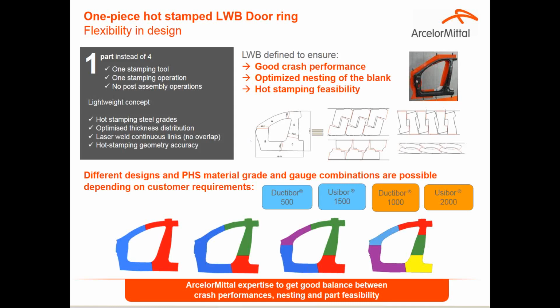From the lightweighting concept, what you derive is the combination of different grades. As we all know, for a majority of our customers today, the side structure has a lot of press hardened steel, and so you can combine the different press hardened steel parts into one part using laser welded blanks. You can optimize the thickness, so you have the right thickness in the right place, and as I mentioned, the no overlap condition through laser welded blanks in a continuous load path.